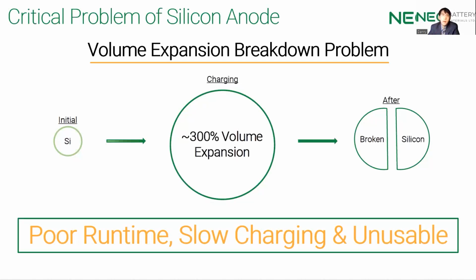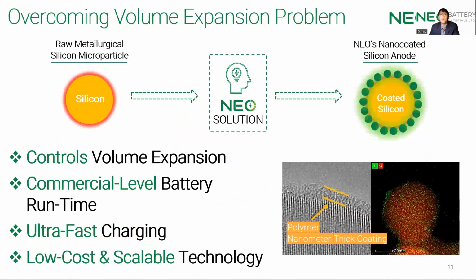So there are not a lot of batteries that are currently utilizing silicon right now. But this is where NEO Battery Materials comes in. Our solution is nano coating materials onto the silicon itself. If you see here on the diagram, the green dots represent the nano coating that's on the yellow silicon particle itself. So what we are able to do is control the volume expansion problem that happens within the silicon. And because we're able to solve the technical difficulty of volume expansion, we can place this into commercial-level batteries, and runtimes are significantly extended compared to graphite anodes itself.